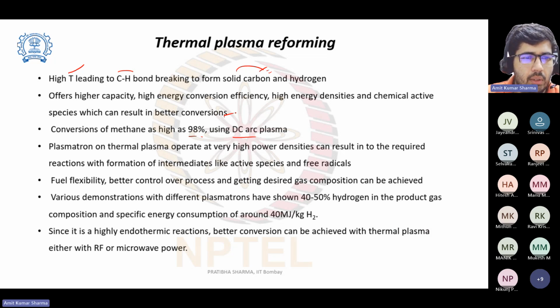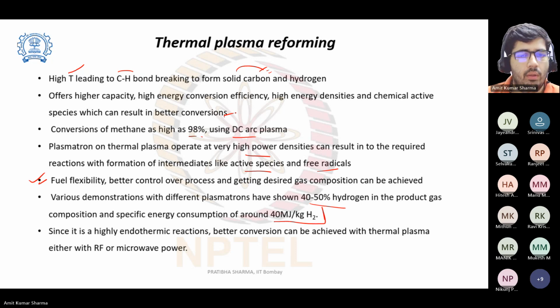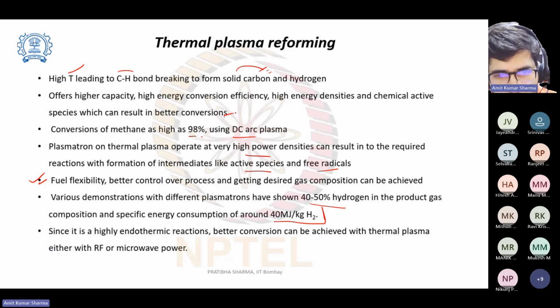The plasmatron, or thermal plasma, operated at very high power densities can result in the required reaction with formation of intermediates like active species and free radicals. It has fuel flexibility. You can see it's operating at very high temperature, so any fuel can be reformed. There is also better control of the process, and the desired gas composition can be achieved. Various demonstrations with different plasmatrons have shown 40 to 50% hydrogen in the product gas composition and specific energy consumption of around 40 megajoule per kg of hydrogen. It is a highly endothermic process. Better conversion can be achieved with thermal plasma, either with RF or microwave power.